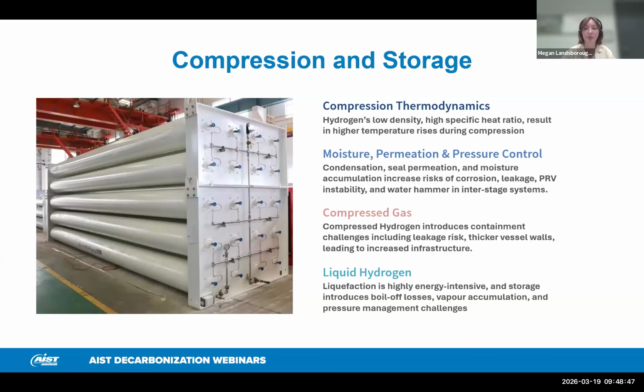In addition, some amount of the stored hydrogen will be lost due to evaporation or boil off. This is especially true when using small tanks with large surface to volume ratios. In order for liquid hydrogen to reach the same conditions as compressed hydrogen, it needs to vaporize first through a phase change. This requires a huge energy shift. Additionally, if you have a tank sitting in the sun, it is incredibly hard to keep the hydrogen cold, and it would actually have a cloud of hydrogen gas inside at the top of the tank. And if the pressure were to build up enough in the tank, it would set off the PSV, and from this, you could lose a ton of your hydrogen product.